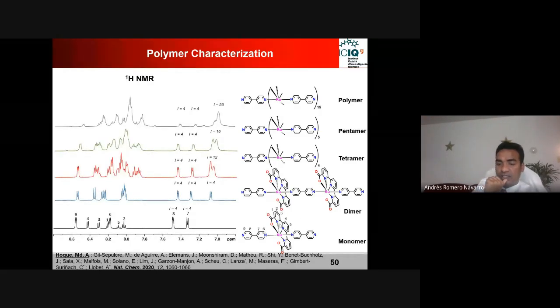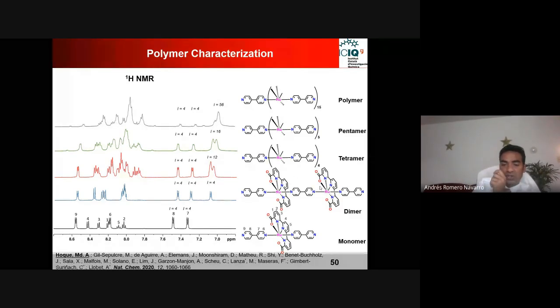So one is this monomer, where we are having only one ruthenium unit. We found that there is a dimer where 2 ruthenium units are there, and then the tetramer, pentamer, and then the polymer we are calling here up to more than 10. So it should literally be an oligomer, but in coordination chemistry we are calling this one a polymer. And how can I identify and characterize those molecules?